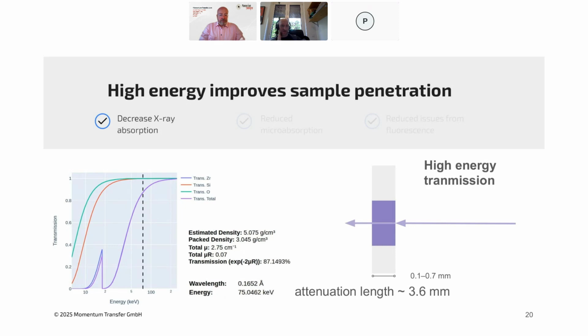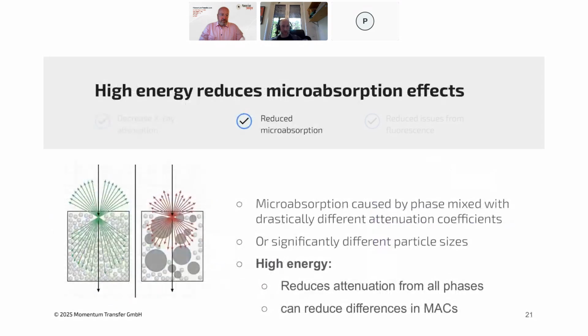With 75 keV for our setup, now your linear attenuation coefficient goes to 2.75 and attenuation length is 3.6 millimeters. So even working with a 1 millimeter sample, now we can pass through much more, a much wider thickness of our sample and probe through many more different particle orientations. And we don't have to deal with this issue of significant absorption artifacts or quenching of our signal.